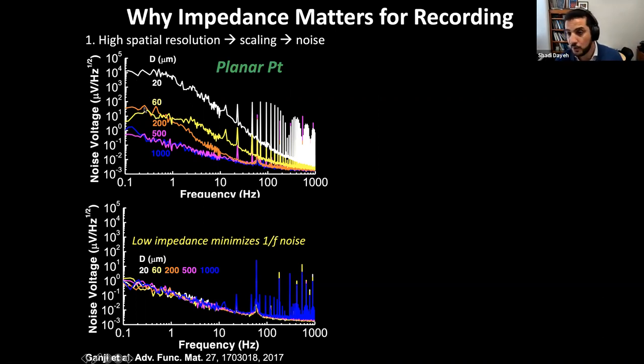So this is 1/f noise that really climbs up to the sky, basically, when we go to smaller diameters. On the other hand, if we use low impedance contacts, for example, PEDOT, then the 1/f noise is really minimized to the instrumentation noise, right? And there is no difference in the noise between large contact and small contact. The reason is that we have a lot of adsorption sites for ions. So random fluctuations in this vast number of adsorption sites doesn't lead to the 1/f noise.